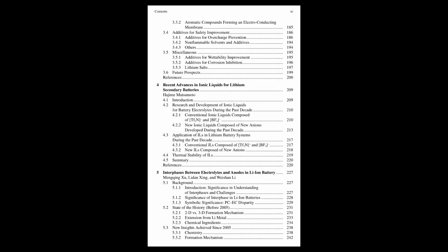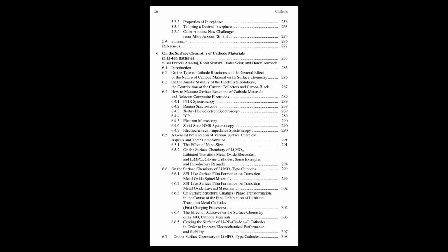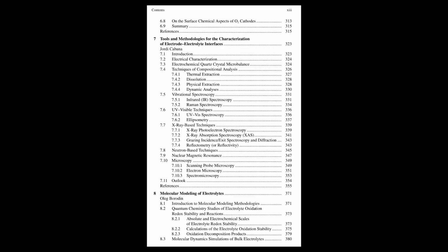The chapter mentions fluorinated cyclohexylbenzenes, discovered in 2002. These can act as redox shuttles, molecules that get oxidized at a specific voltage just above the normal charging voltage. How does that help? When they get oxidized at the cathode, they travel to the anode, get reduced back, and travel back again. This creates a sort of internal short circuit that dissipates the excess charging energy as heat, preventing the battery voltage from rising much further. Clever, like a safety valve. Kind of, yeah. It also discusses other compounds like 2,5-di-tert-butyl-1,4-dimethoxybenzene, which could be useful for lithium iron phosphate, LiFePO4, cathodes, and phenothiazine compounds, which were shown to be effective by Jeff Dahn and his team in the mid-2000s. Different molecules, often working by similar principles of getting oxidized at a set voltage.